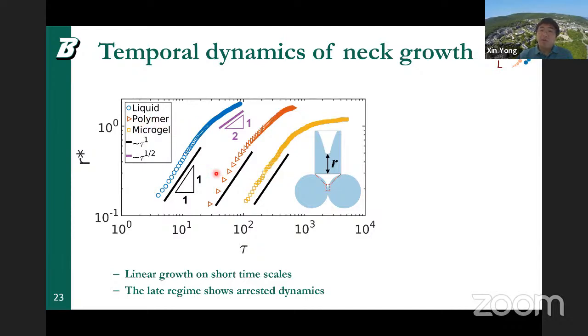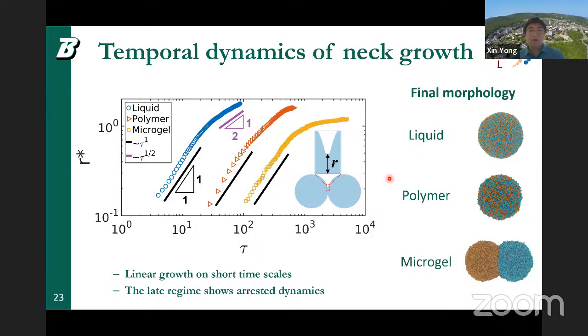As we can see here, surprisingly, these three cases exhibit very similar dynamics at early time, where they all show a characteristic linear growth, which resembles a Newtonian fluid. However, in a long time scale, it's obvious that they behave very differently. For microgel, the neck growth is very arrested, and then they basically flatten down. And so this final morphology is also very different. For liquid and polymer, they will finally merge and completely mix with each other, while microgel just forms dumbbells.